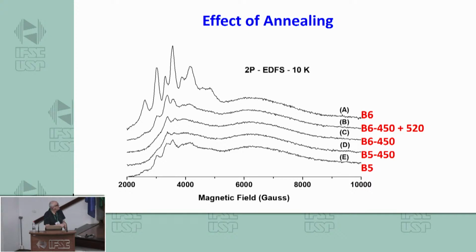Upon UV exposure, the signal becomes much bigger. And then when you do thermal treatment, it goes away. So basically this antimony species is probably getting oxidized, and is then no longer the Sb4+ species that it would have to be to give a signal like this.